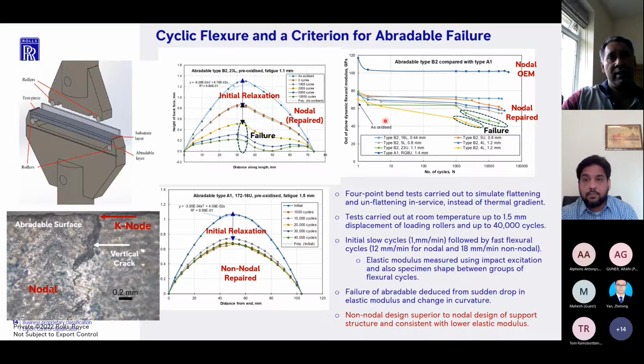What I've done here is plot the elastic modulus that we measured in the interrupted test over a number of cycles. The displacements indicated here are the displacements that we applied. We went from around 0.4 to about 1.2 or 1.4 millimeters.